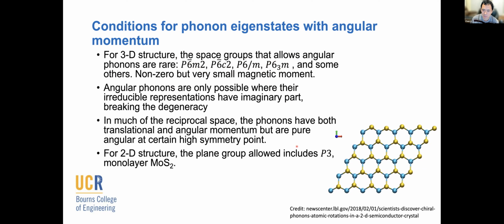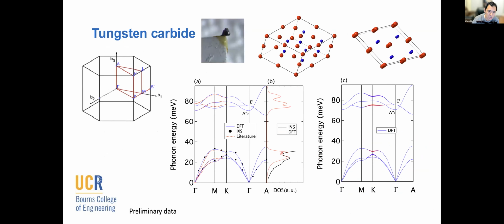And obviously, if it's 1D, it's easier to work with, but we're working with bulk systems, which means finding broken inversion symmetry is harder. One material we were able to find was tungsten carbide. This is a material system with a reasonable scattering cross-section and with nice phonon energy to work with. In addition, we can get a hold of good quality single crystals.